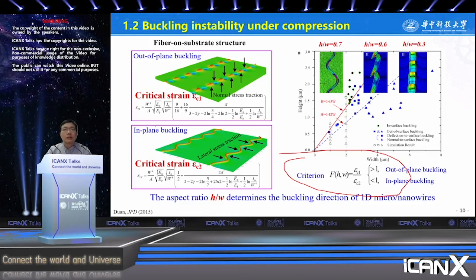Theoretical analysis and numerical simulation discover that the ratio of height to width is a critical factor to control the buckling competition. The right figure presents the influence of the cross-section of the structure on the buckling mode. The inset figures are the FEA, finite element analysis, results of the buckling in the cases of aspect ratio equal to 0.7, 0.6, and 0.3. So it's a significant help to fabrication, since the buckling is mainly determined by the cross-section rather than the material. This is very useful in manufacturing.